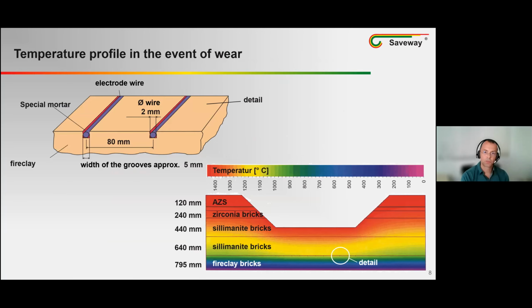The sensor electrodes are embedded in fire clay. The current from one comb passes through the refractory material to the molten glass and then returns to the other comb next to it. In this way, we determine the electrical resistance of the local refractory material. Because we can know in advance the thermal conductivity of the lining and the resistivity at each temperature, we can calculate the temperature distribution in the lining, just like the different colors shown in the picture.